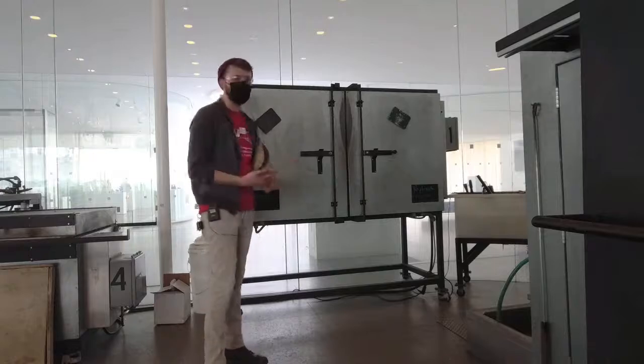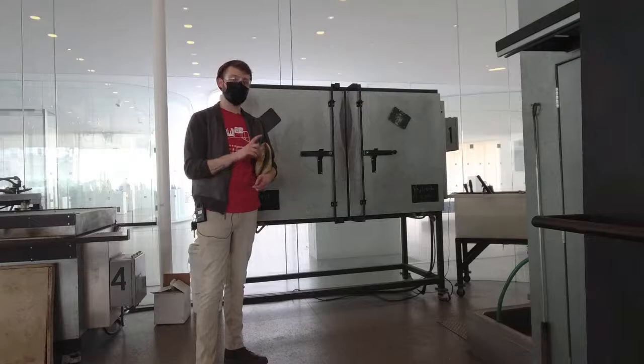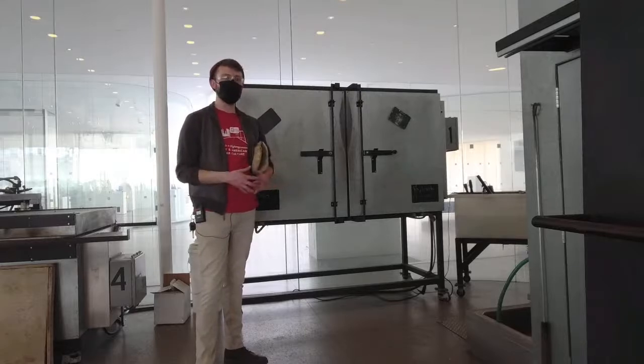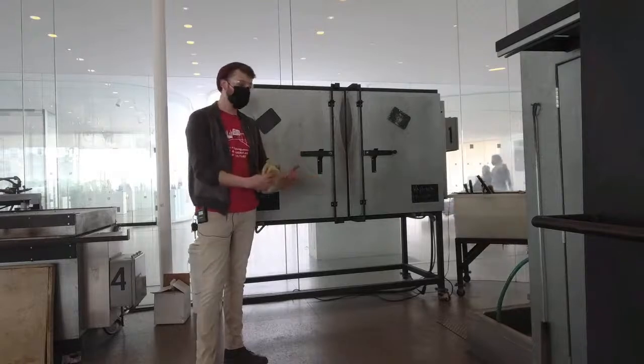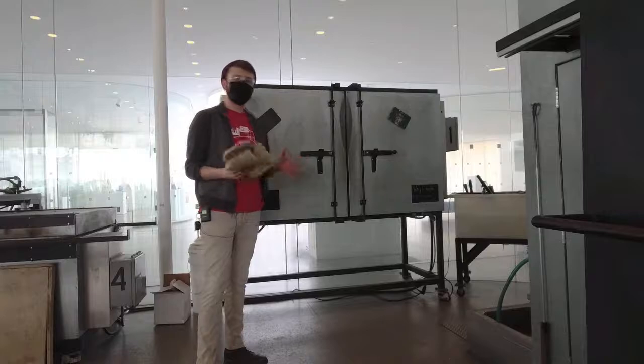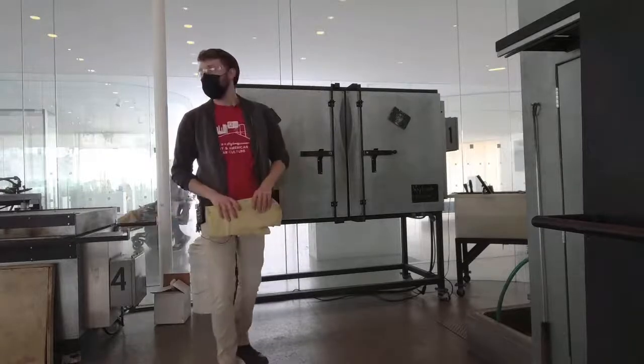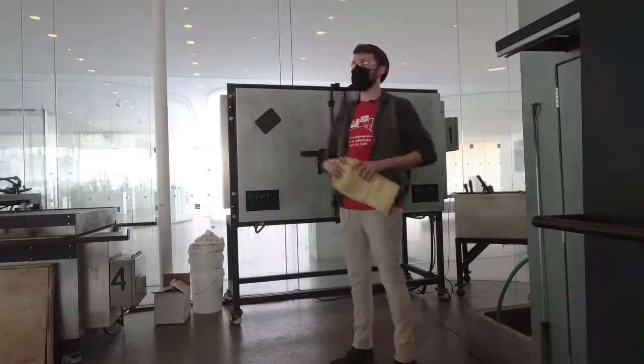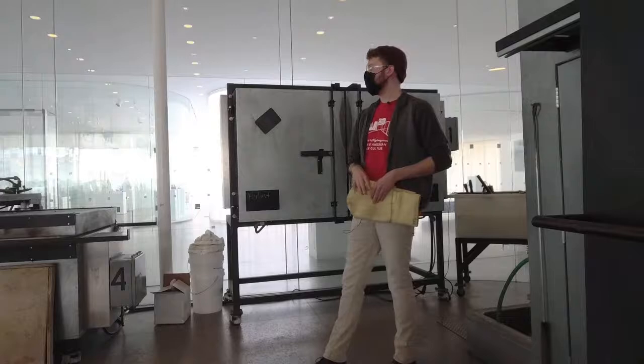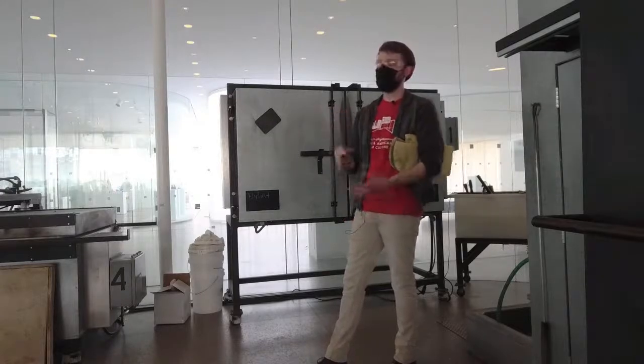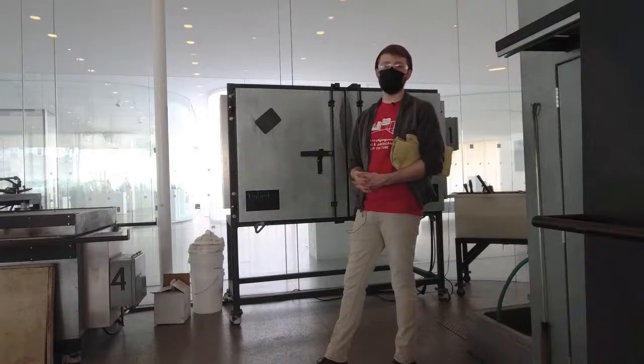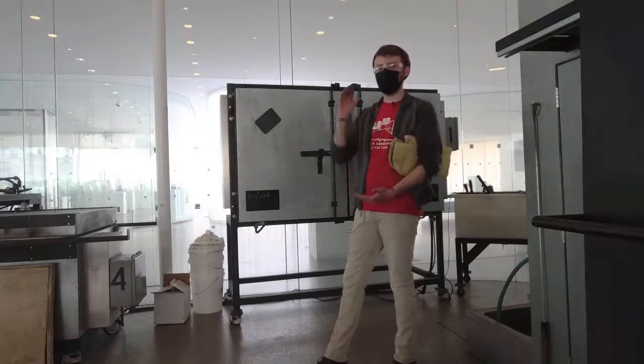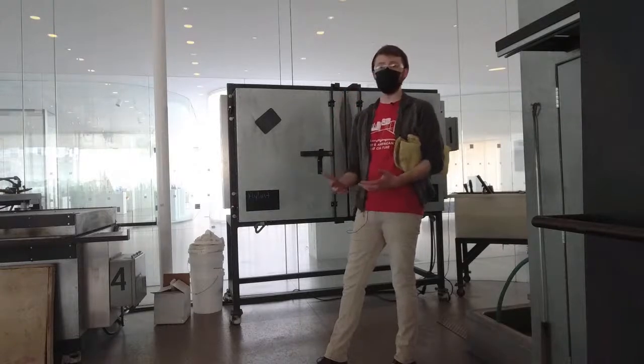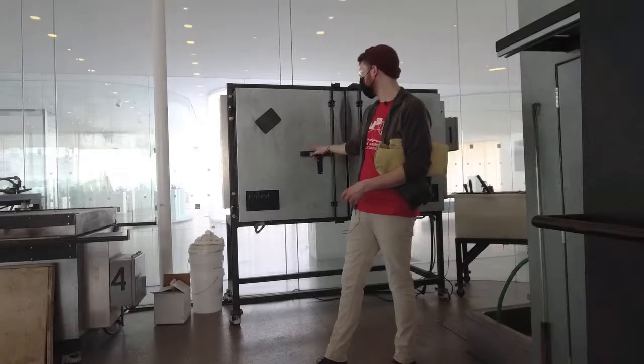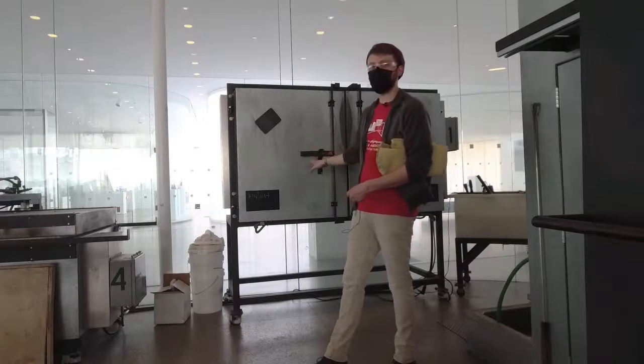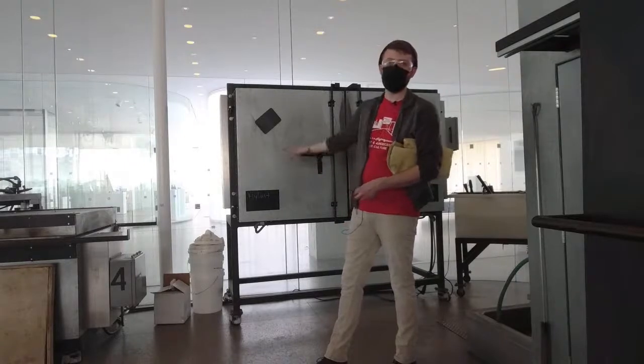The cycle or the time that it takes to anneal glass is solely dependent on the thickness of the material and also the type of glass that it is, whether it's soda lime glass like we have in our studio here, or quartz glass or borosilicate. They all play a different role in the annealing of the material. For those of you who are familiar with the Glass Pavilion in our collection, you all probably know about the solid glass bench in our ancient gallery. That glass is 3 foot thick, cast into sand, and that piece took about 11 months to anneal fully. That's an extremely long time, but that extreme thickness of the glass really determines how long it's going to take to cool it down. So annealing is a very important part of our process, but it's into the more scientific area of glass making.